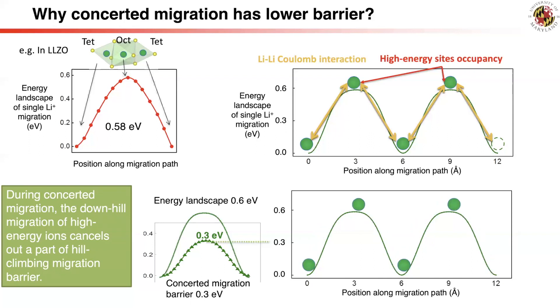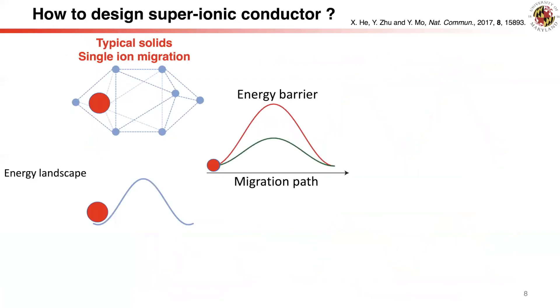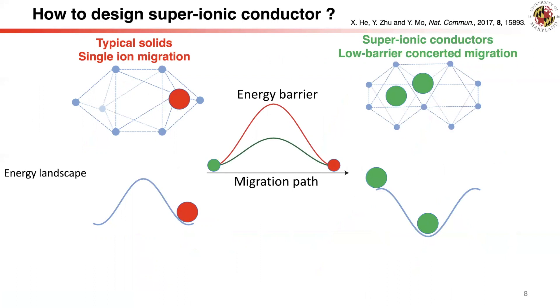As a result, a lithium ion on a high-energy site migrating downhill cancels out part of the total migration energy during concerted migration. In summary, in a typical solid, ions hop over a barrier individually, while in superionic conductors, some ions occupy high-energy sites, activating multi-ion concerted migration to produce a low energy barrier.